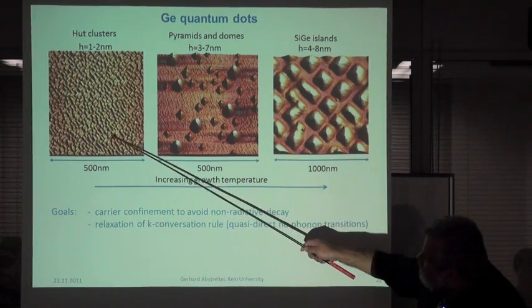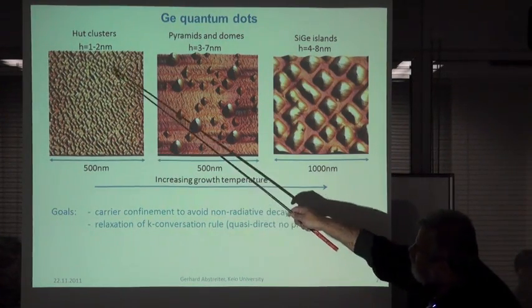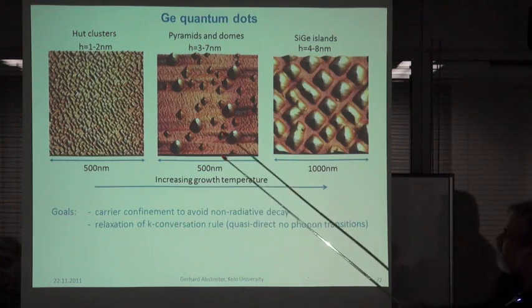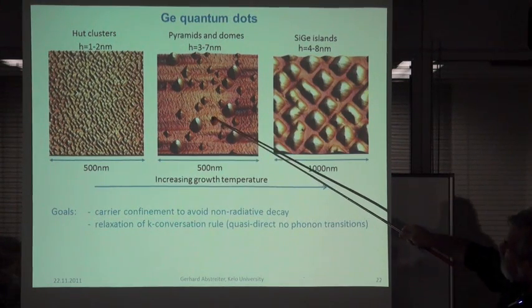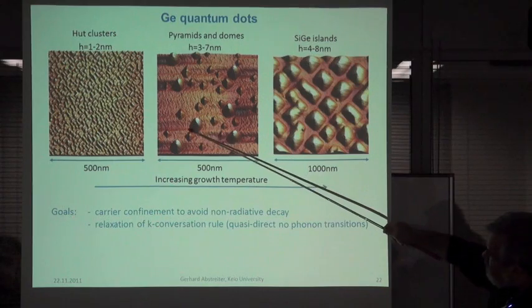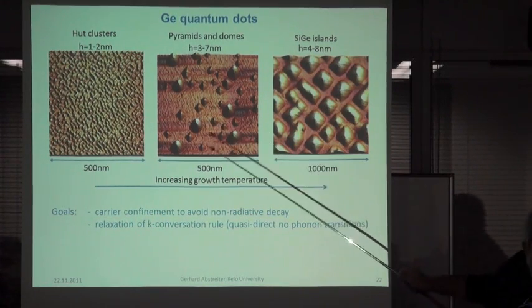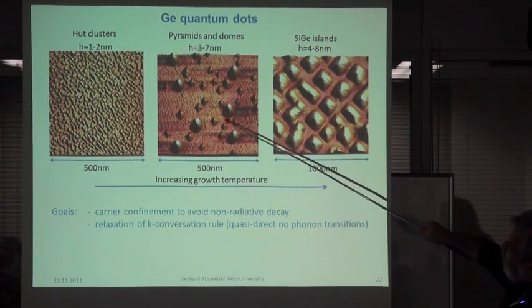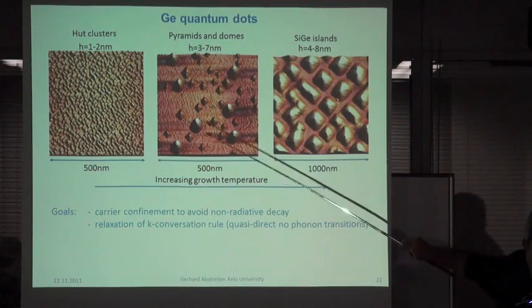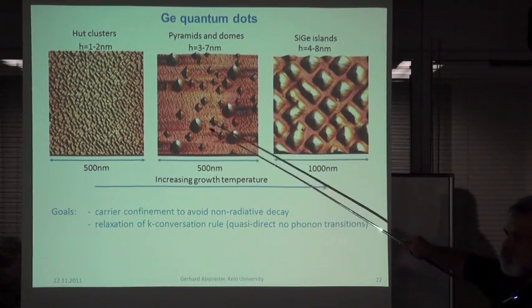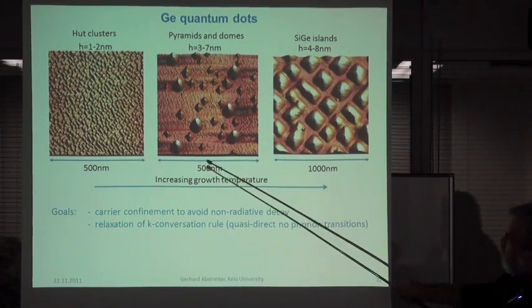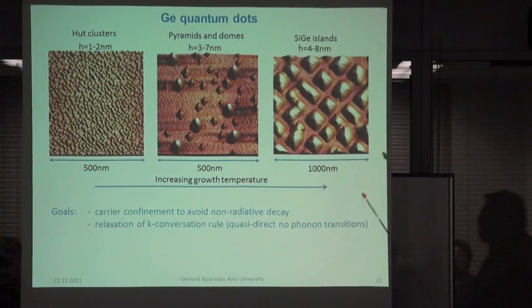You get these very small hut clusters, which have a height of 1 to 2 nanometers, or you get these pyramids, or a mixture between pyramids and, in the literature, what are called domes, which have different facets here. But you can have quite pure pyramids only, or a high density of these domes in such a system. So this is a scale of 500 nanometers.